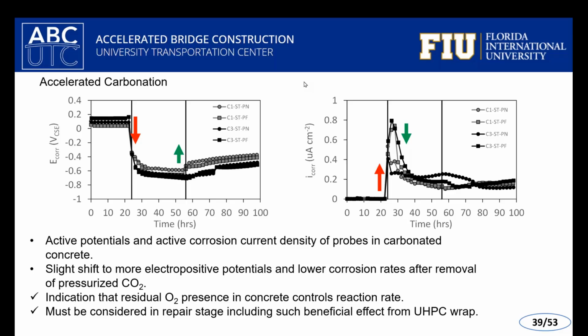Notably, the second vertical line, the stripe that you see in the curve, represents when we released that gas, when we shut off the valve. And we noticed something: there was a little bit of recovery, shown by the green arrow. So where we had a fairly electropositive potential before carbonation, upon carbonating it, corrosion develops at a much more negative potential, and then it recovered after the CO2 was removed. So this is indicative for us that there's some type of recovery of oxygen coming to the system.